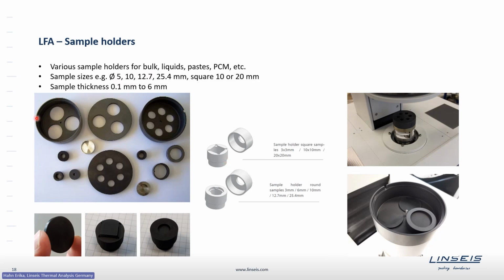On the left, you can see the carrier for the sample robot for 3 samples and for 6 samples. Within each position, one can place an individual sample holder, meaning that within one carousel, you can have up to 6 different sample holders, also with different geometries inside. The sample holders themselves are designed as follows. We have the carrier for the sample, and in addition, a lid for the case that the borders are not closed completely and some light would directly penetrate to the detector. This we want to avoid, and because of that, we have the lid.